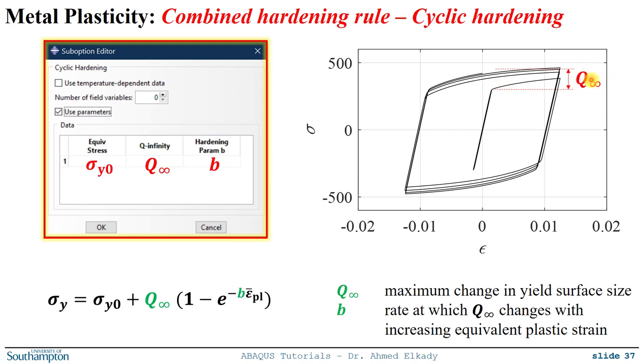The Q infinity has the units of stress. So if you are using Newton per millimeter square, MPa, then Q infinity will be in MPa. And B is the rate at which Q changes with increasing equivalent plastic strains. Because if you see here in this example that I'm showing, let's say that you are specifying Q infinity to be 100 megapascal. So if you start from 300 megapascal at the initial point, cyclically with increasing cycles until the point of saturation, you are going to reach 400 megapascal. But how is this reached?